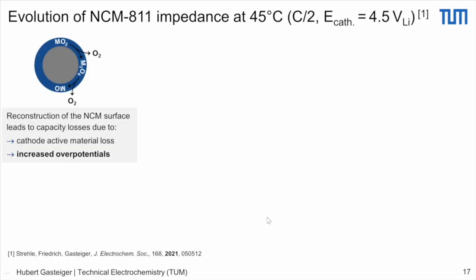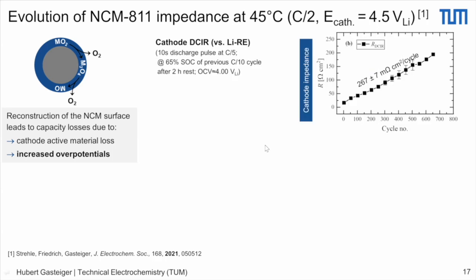So what we want to look at is, one part of the overpotentials, of course, we can quantify, that's the charge transfer resistance of the cathode active material. And this we measured by two ways. One was by a DCIR pulse versus the lithium reference electrode. So in principle, you measure mostly the cathode response. And what we can see here is that the impedance increases quite dramatically over these 700 cycles.